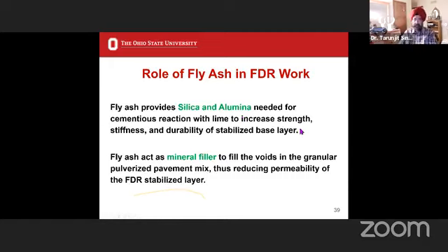And you know that the lime that we add allows the pozzolanic reaction, but they need silica and alumina, which comes from fly ash. And the fly ash also acts as a mineral filler. It fills in the larger voids that you have once you pulverize the base layer and the subbase layer. As a result, the permeability is reduced. So the second part reduces the permeability of the stabilized layer, the base and subbase, so less water infiltration happens. And the first one, the pozzolanic reaction, increases strength, stiffness, and the durability.